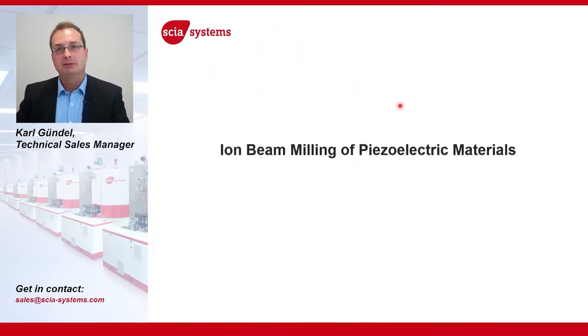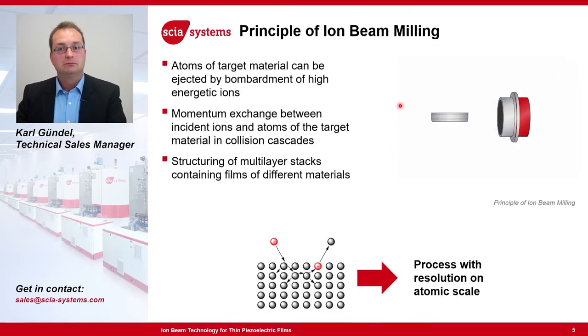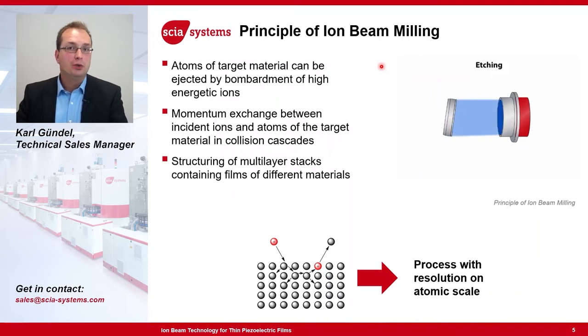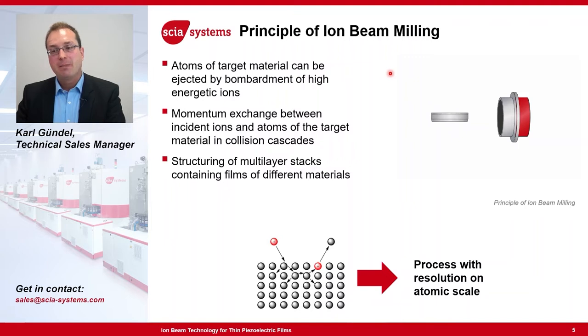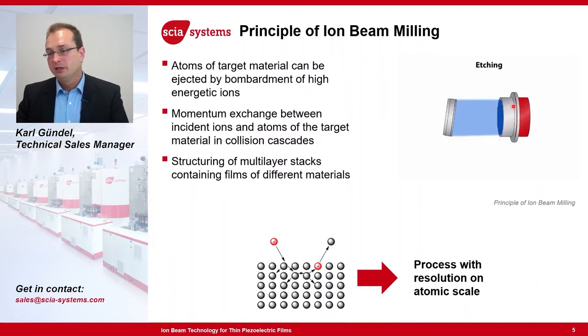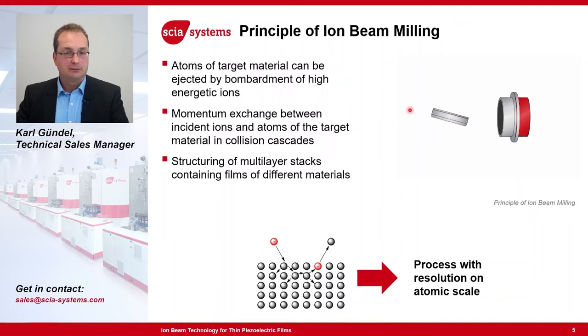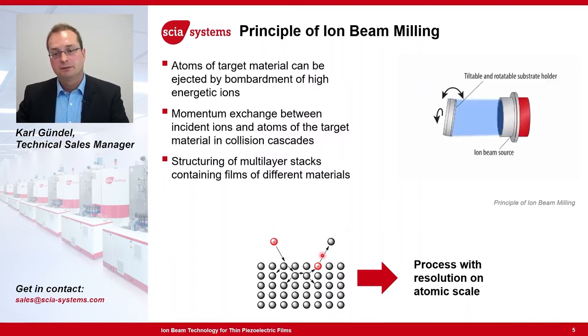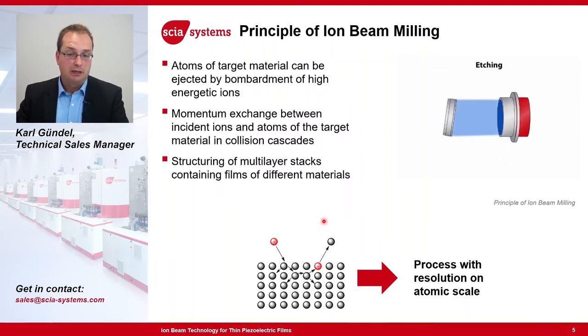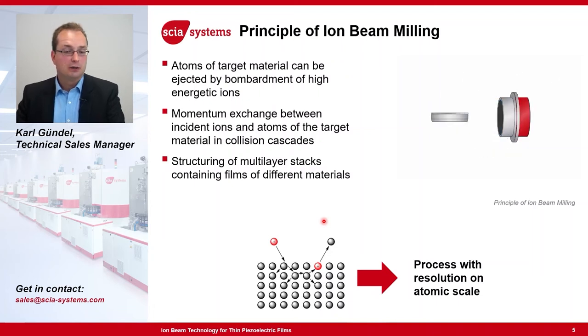Coming to the first technology which enables structuring of piezoelectric materials — the technology is called ion beam milling, because you etch the substrate surface by ions. These ions are generated in an ion beam source with a plasma chamber, and out of this plasma the ions are accelerated by a grid system. These ions are formed as a beam, and this beam is directed on the substrate surface where you generate a collision cascade. By this, you sputter out the top atoms of the substrate surface, achieving etching of the surface. And if you have a mask on top of your substrate surface, you can do structuring on a very low lateral dimension.